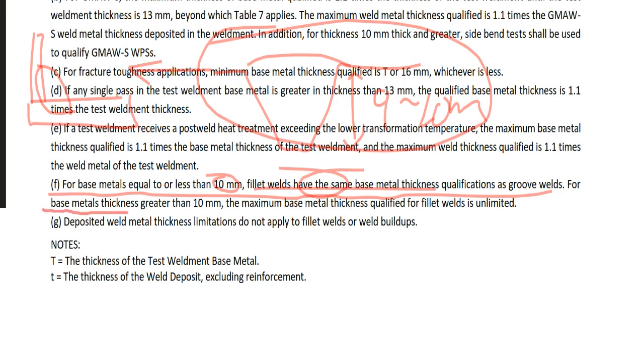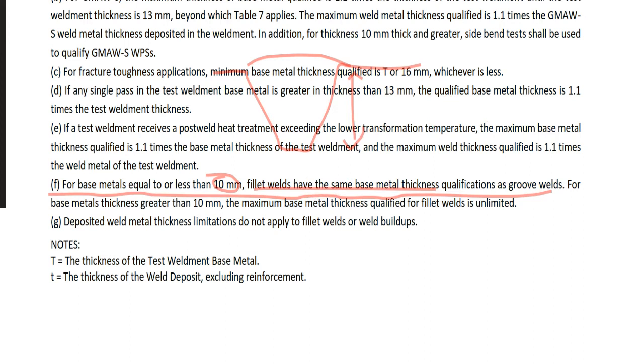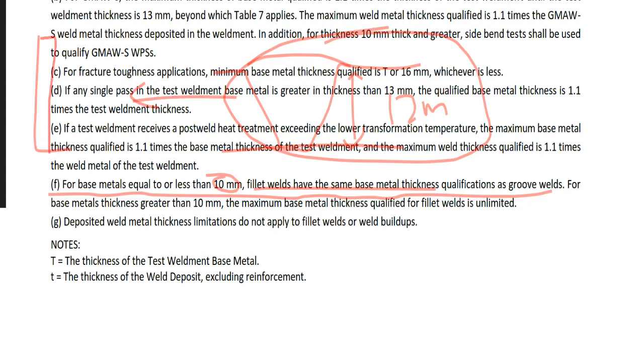For base metal thickness greater than 10 mm, the maximum base metal thickness qualified for fillet weld is unlimited. So if this thickness is 12 mm, then this groove weld thickness qualification can qualify this fillet weld thickness qualification, but this is unlimited.